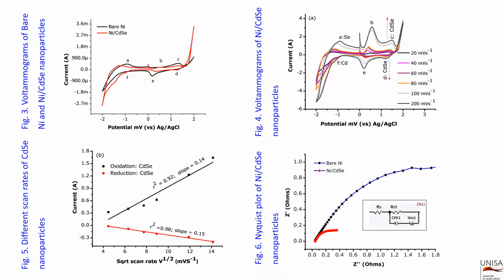The calculated diffusion coefficient was found to be 2.9 into 10 power minus 6 centimeters square, with a correlation coefficient of 0.98, and the surface coverage was found to be 1.38 into 10 power minus 3 mole per centimeter square. The calculated values reveal the formation of a monolayer at the electrode interface and a diffusionally controlled system, which indicates it is highly catalytic and can be applied to various electrochemical systems. To confirm the electrochemical kinetics at the electrode interface, impedance was measured as shown in figure 6.